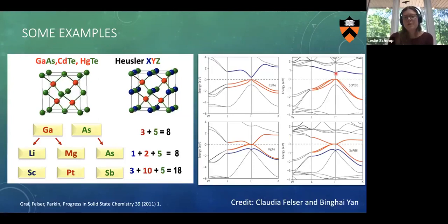Just pointing out that if you go down the periodic table to very heavy elements, like here with bismuth or mercury or tellurium, sometimes this band gap closes, but you still have something which is called a semi-metal, where you will have either a touching point of bands or equal amounts of electron and hole pockets because you have this charge balance. Okay, great. So this sounds super simple. That sounds like everything you need to know about chemistry is how to count to 8 or 18 and you're done. And I mean, that would be sweet. Life would be so simple, but sadly it's not always that simple.